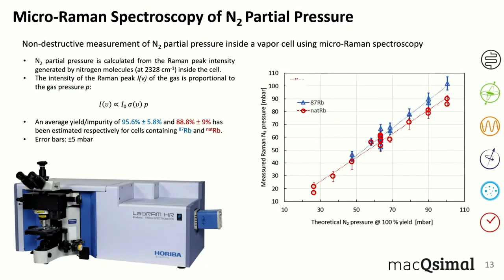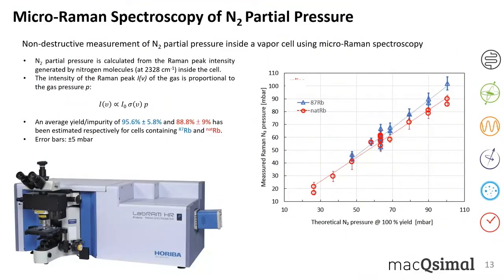Okay, but we also characterized the nitrogen partial pressure with a micro-Raman spectrometer that we have in our lab, and we established a very nice protocol which allows us to make a non-destructive measurement of the nitrogen partial pressure. With the Raman, you can only see diatomic molecules, so we don't see the argon, but we see the nitrogen. We have a vapor cell that we dice in a way that it is completely open, and then we make a reference measurement of just air, and we know the composition of air and the partial pressure of nitrogen in air, and then we compare this to the measurement of the cell itself.